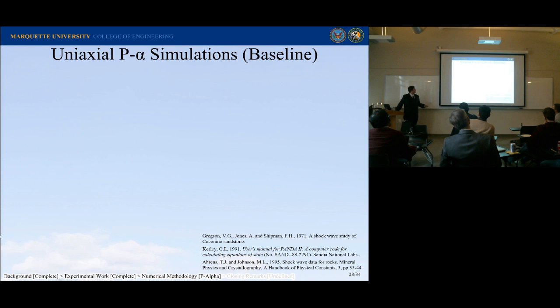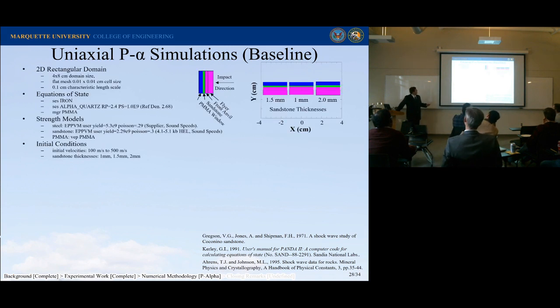So I started off with this P-alpha simulation, and a P-alpha model just assumes that some sort of heterogeneous material has porosity properties. So it's not great, but it's a good first guess. And so I had this 2D rectilinear domain. I put in some equations of state. You can see I used the alpha quartz model based on what I have, iron and PMMA, because those are the materials that I'm using to hold it. And then I have the strength models.